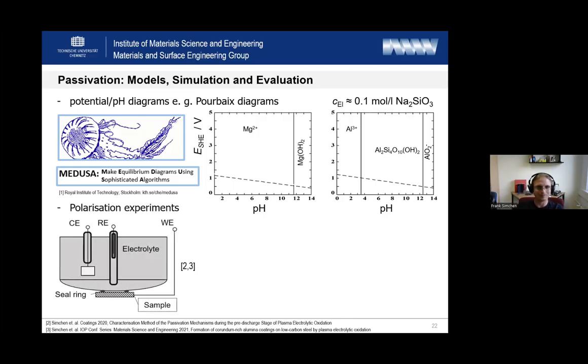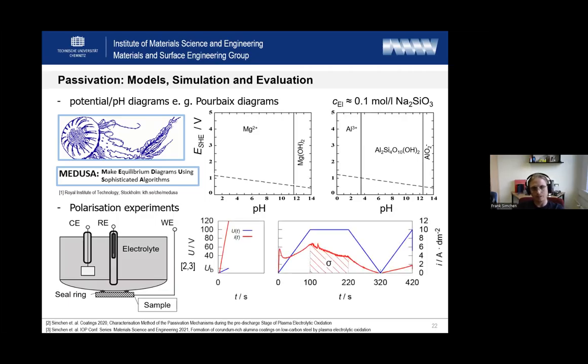So theory also doesn't help so often. So we need also an experimental method, and we still don't want to prepare every time 10 liters of electrolytes before we start an experiment and find out the system is not working. So that's why we developed an electrochemical method, which we are using to pre-select suitable electrolyte substrate combinations. We apply here our metallic sample below an electrochemical cell, have here a sealing ring, and here a really low electrolyte volume of maybe 250 milliliters.